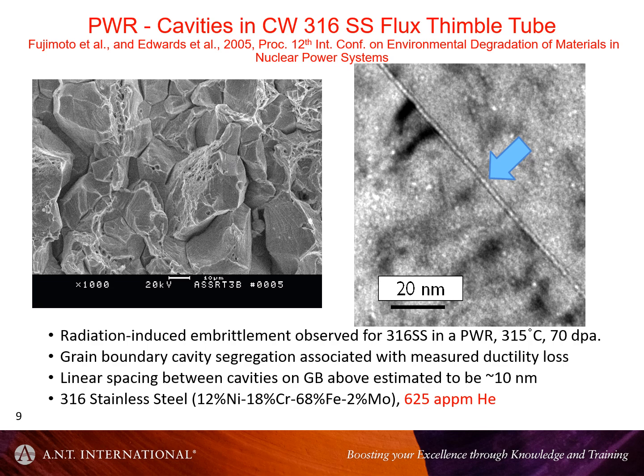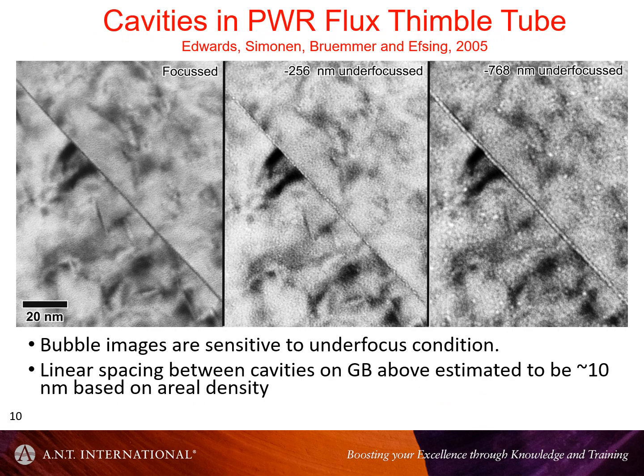So this is stainless steel. It's only 12%, 13% nickel, so you don't get an awful lot of helium. Plus it's a PWR spectrum, so it's not like CANDU, but enough to get this segregation. And people hadn't noticed it before in any other previous TEM studies of stainless steels. And Danny Edwards at the time kind of attributed this to the fact that people hadn't defocused the TEM.